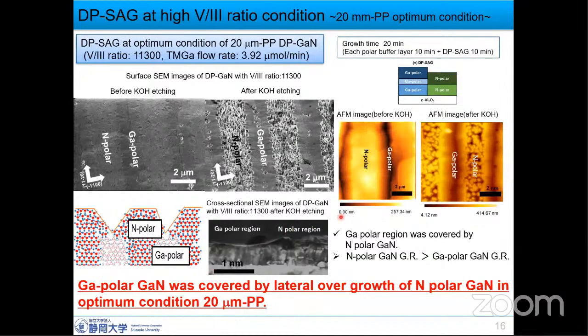Next, I'm talking about DP SAG at high V/III ratio, 11,300. This V/III ratio was the optimized growth condition of 20 micrometer pitch pattern DP GaN. So DP GaN was fabricated at this condition. Following the surface SEM image, each polar region was confirmed, and in the surface SEM image after KOH etching, DP GaN was etched periodically.